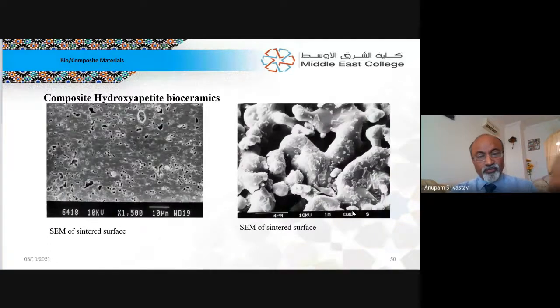When we go for higher magnification, we can see these pores. The left-hand side pores are not desirable because they are not big enough. They won't allow growth of tissue, veins and nerves. Whereas on the right-hand side, it has been intentionally created like that, so that pores are available. The size is good enough to allow at least a minute level of growth, and that will make the implant stronger and serve longer.